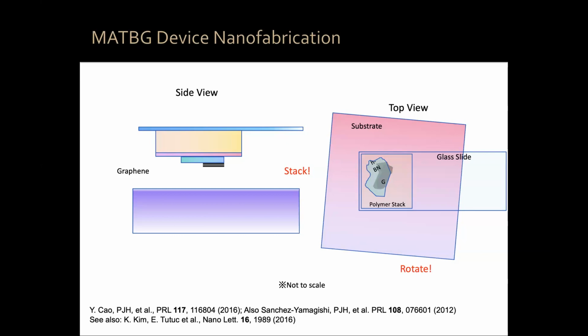As I said, this thing is extremely sensitive. The magic happens between 1 and 1.2 degrees more or less. So you have to have micropositioners and goniometers and everything that is stable on a 0.01 degree scale to get this thing reliable. But it's not exquisite engineering. You buy commercially off the shelf things and they have that accuracy.